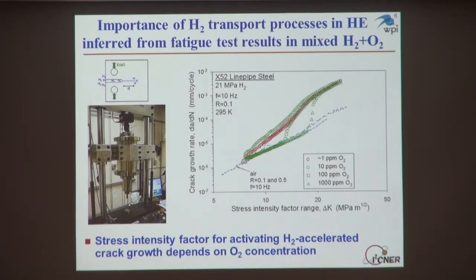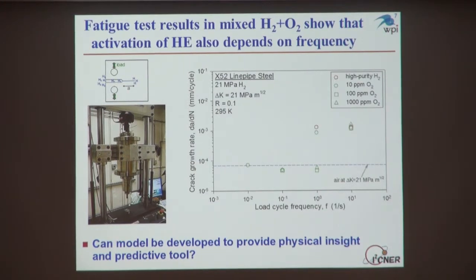So all of these tests were done at a constant load cycle frequency. That is the frequency where we apply the cyclic loading. What I'm going to show you on the next slide are some tests that were done at a fixed stress level, but now we're going to vary the frequency of the loading. This is the same type of testing, the same type of apparatus, but now when we look at the crack growth rate versus the load cycle frequency, starting at this value of 10 hertz, which was representative on the previous slide, as we decrease the load cycle frequency, we see that eventually the crack growth rates come all the way down to the crack growth rates in air. And the frequency at which these rates decrease depends on the oxygen concentration.